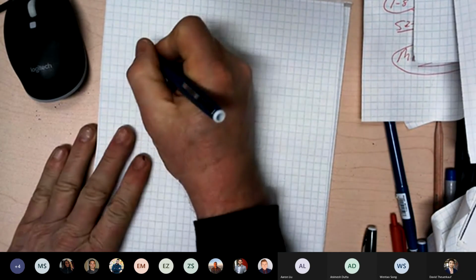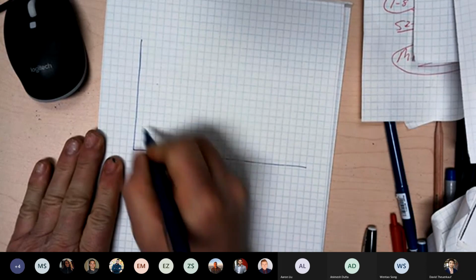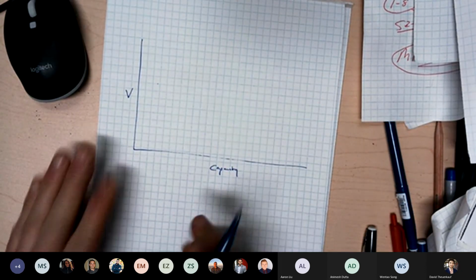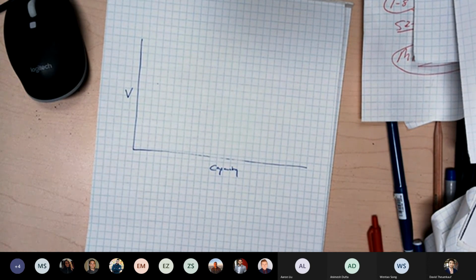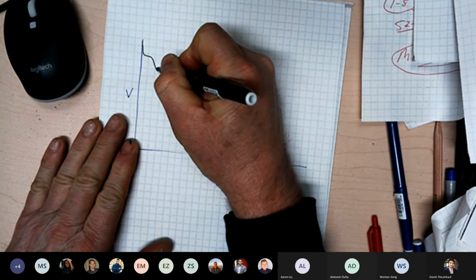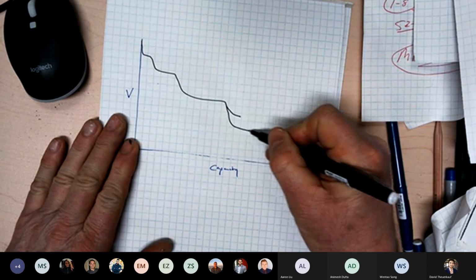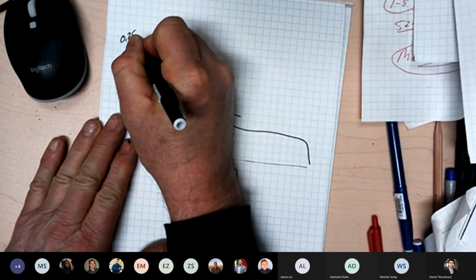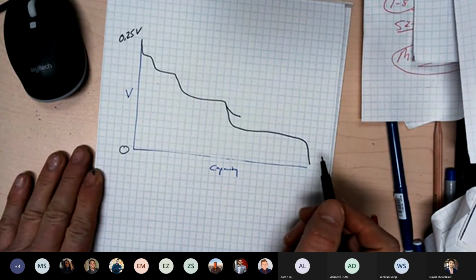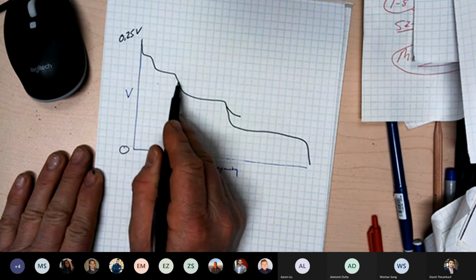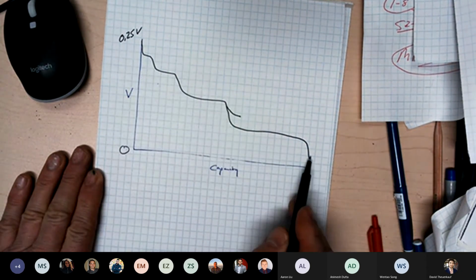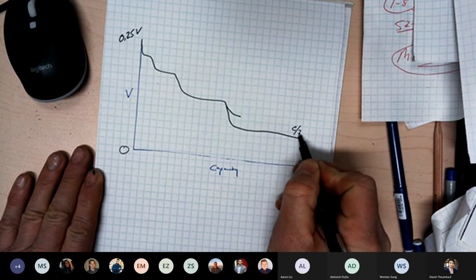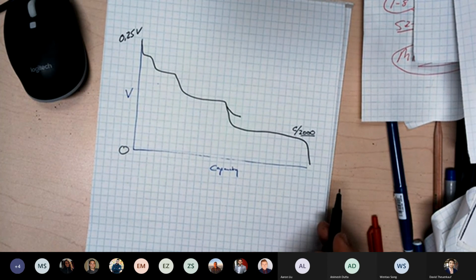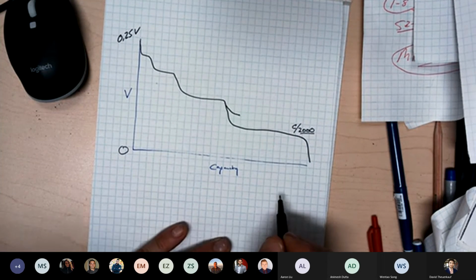So let's talk about graphite. We're going to plot the voltage capacity curve on a very blown up scale. So this might be 0.25 volts versus lithium metal. And this is 0. This is what you would measure if you measured incredibly slowly, both adding lithium and taking it out. So this might be C over 2000 rate. And actually, we have data in our lab for lithium insertion and removal in graphite measured at a C over 2000 rate that Chris Burns measured. Could I find it? I doubt it. I don't know where it is.